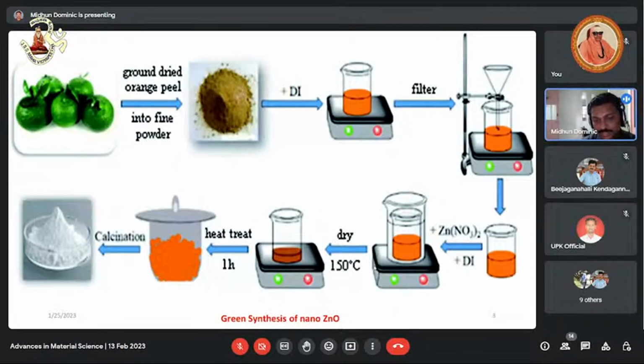I will demonstrate a simple example by the preparation of zinc oxide nanoparticles. Zinc oxide nanoparticles can be chemically prepared by sol-gel method, chemical precipitation method, etc. Here, this schematic diagram represents the preparation of zinc oxide nanoparticles using orange peel extract. First of all, the orange peel is dried and ground, and we powder it, and it is treated with deionized water and mixed with zinc nitrate solution. We heat it at 150 degrees Celsius, followed by calcination at around 450 degrees Celsius. We may get zinc oxide nanoparticles.